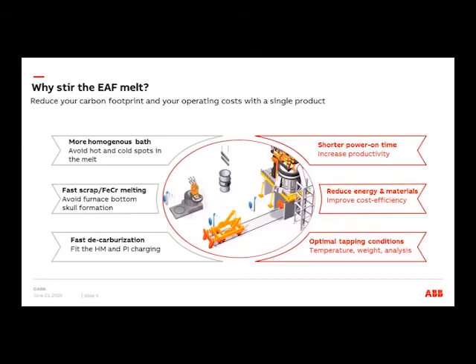So why do we want to stir the electric arc furnace liquid metal? We know, for example, that the process in the electric arc furnace is far from equilibrium, both in temperature and in chemistry. So when we are stirring the liquid metal, we will have a more homogeneous bath. We will avoid hot and cold spots in the liquid metal. We will have faster scrap melting, especially true for big sizes of scrap. We will have better ferrochromium melting and dissolution. We will also avoid furnace bottom skull formation. We will also have much faster decarburization with a higher oxygen yield when we are blowing in the oxygen. This will fit hot metal charging and pig iron charging. And also we will have better temperature prediction, which gives a much better endpoint prediction.